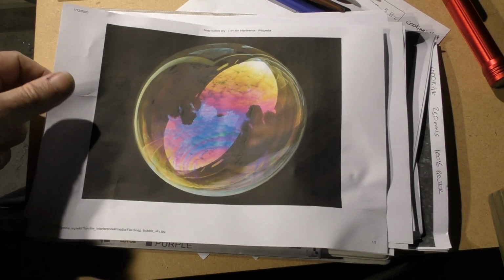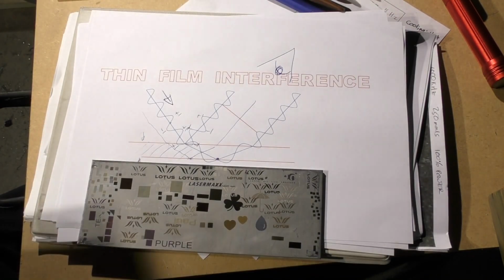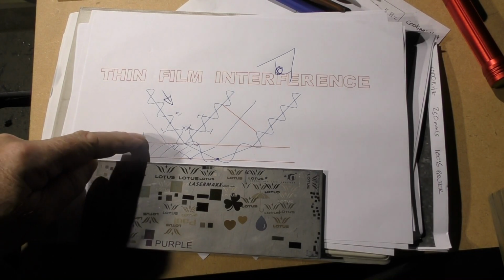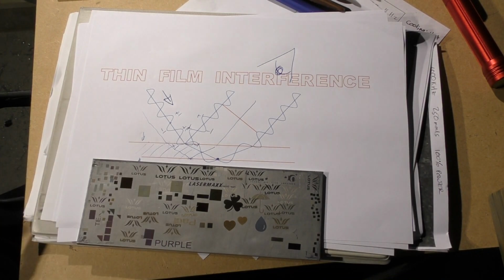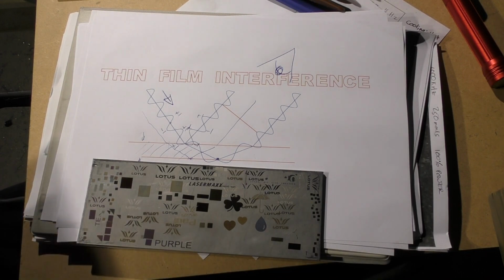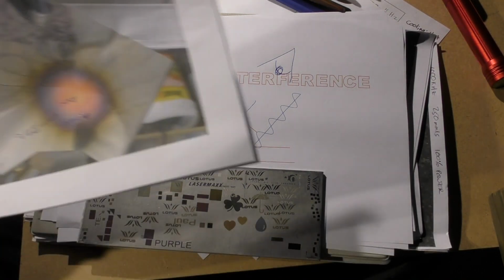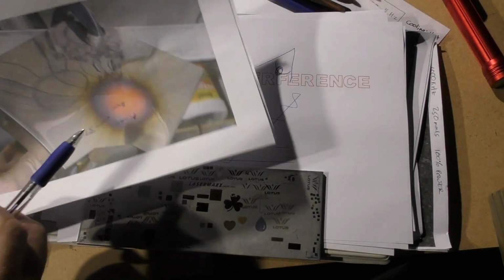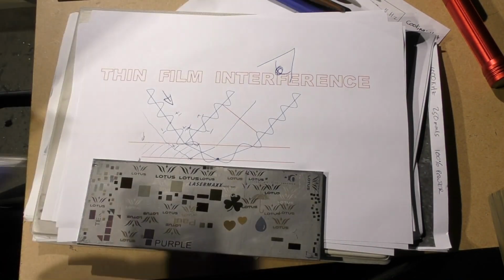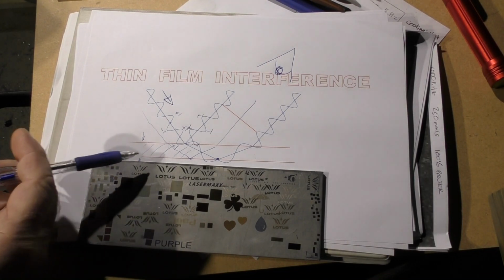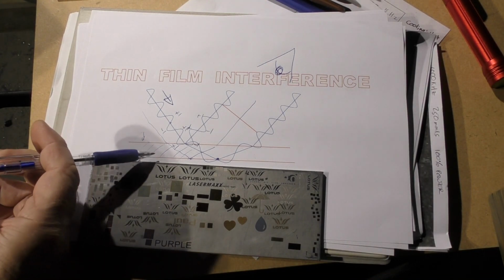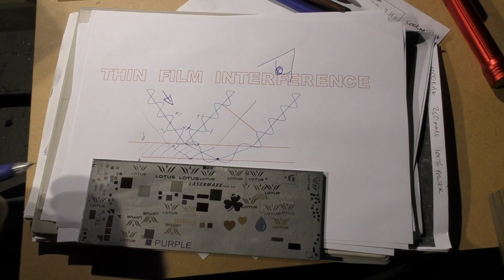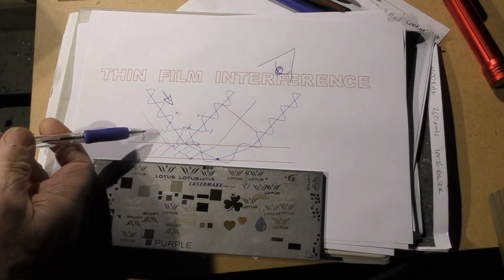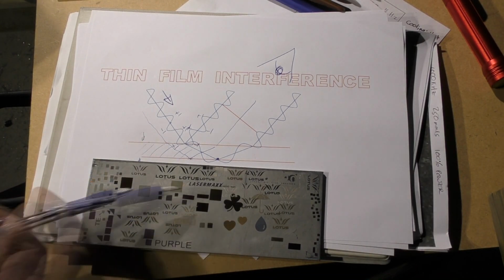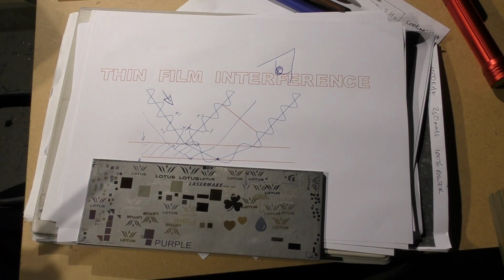We have to draw the conclusion that the only thing that the heat is doing is changing the thickness of this film. So I'm afraid there is no magic pen that this machine has which paints different colours on the surface of stainless steel. It doesn't even require heat to produce these colours. It needs a thin, transparent film. We're going to have to manipulate the thickness of this film to produce these non-pigment colours.